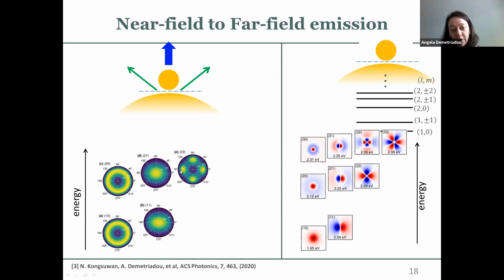The 2,2 mode emits at more or less the same angle as the cone of the 2,0 mode and the 1,0 mode. However, it has 4 lobes, which correspond to the 4 lobes that you have in the near field here in the gap. So if I place a dipole in my gap exactly in the center, because all these modes are 0 in the center, it won't couple efficiently to them. It will only couple into these ones. So if I put it exactly in the center, it will emit in a conical way.